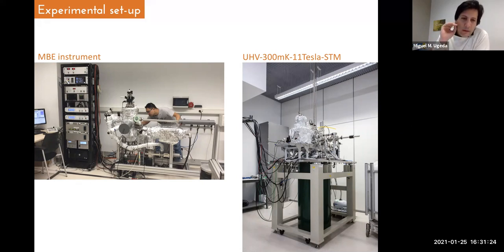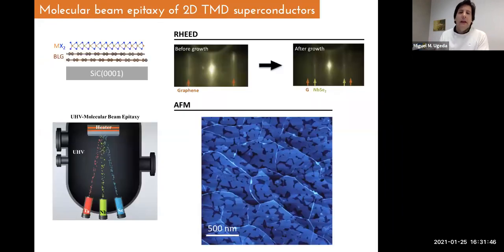So once we have grown this material, we basically cap it with amorphous selenium and we transfer it through air, that's not a problem, into our STM system, which operates at a base temperature of 300 millikelvin. We have the possibility to apply 11 Tesla to it. And it's working under ultra high vacuum conditions. Okay, so for those of you who are not familiar with MBE epitaxy, basically the way we proceed is to deposit the elements that we want to grow.